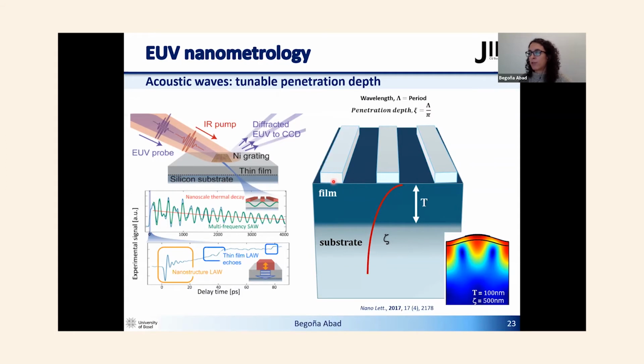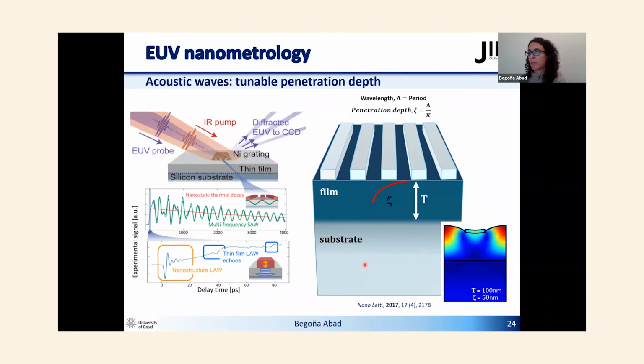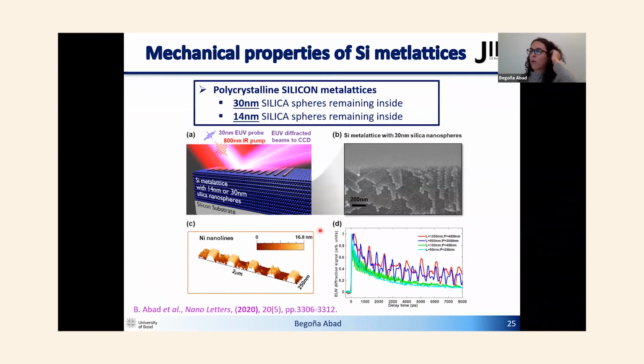So if we are able to tune the period between these lines, we are able to tweak this penetration. That means that for large periods, the acoustic waves reach the substrate. But if we go to sufficiently small periods, we are able to confine the wave within the film. And this allows us to decouple the properties of the thin film from those of the substrate.